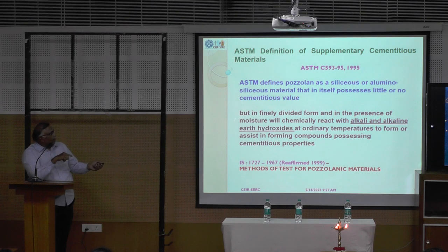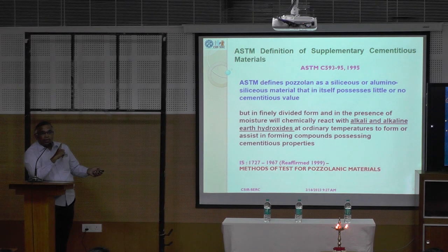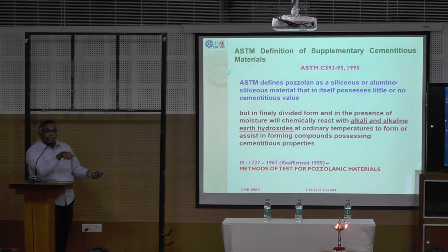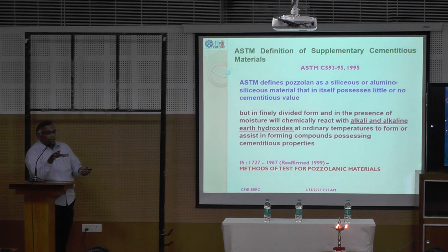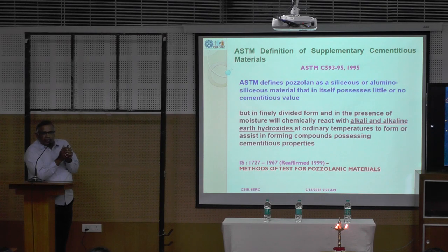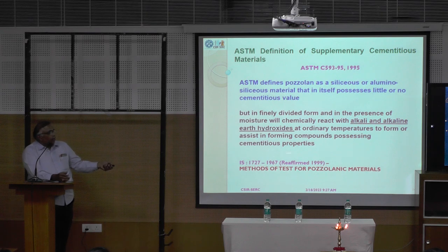Provided, if you are adding with any alkali or alkaline hydroxides — what I discussed sometime back, calcium hydroxide — if the siliceous material is reacting with calcium hydroxide, we will get, at ordinary temperature, cementitious properties formed. The siliceous or aluminosiliceous material reacting with calcium hydroxide gives us additional C-S-H, and we are getting cementitious properties.